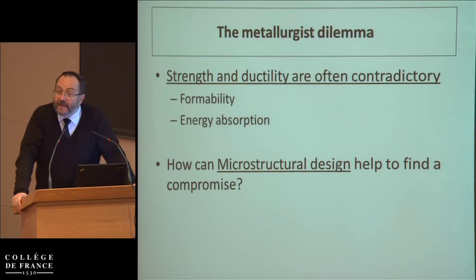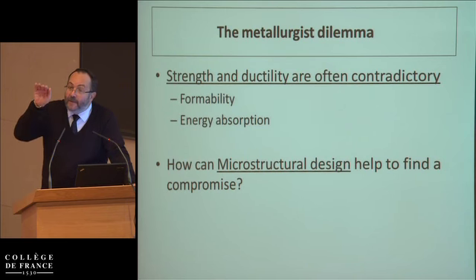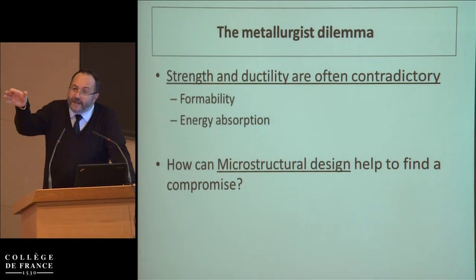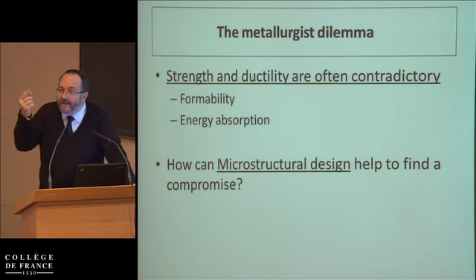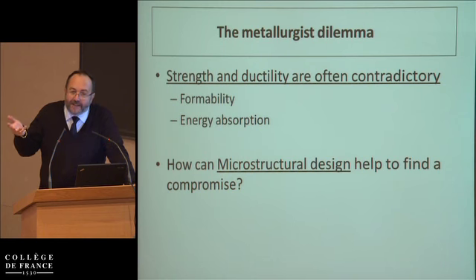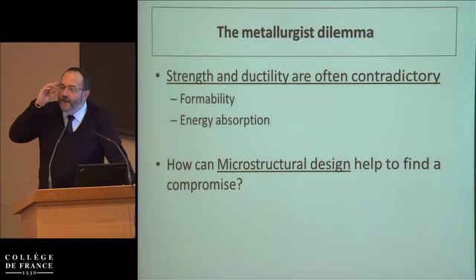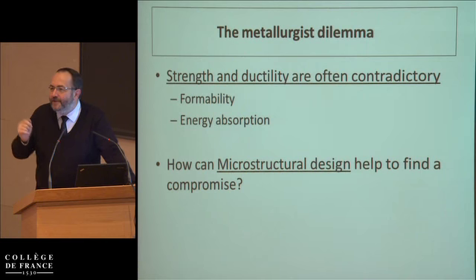So that means that any material which has a high yield strength, which will favor the stress localization, where you have a change in thickness of the sample, will need a high work hardening in order to spread the plasticity instead of localizing it. So that's the intrinsic reason for which, the stronger a ductile material is, the less is the ductility.